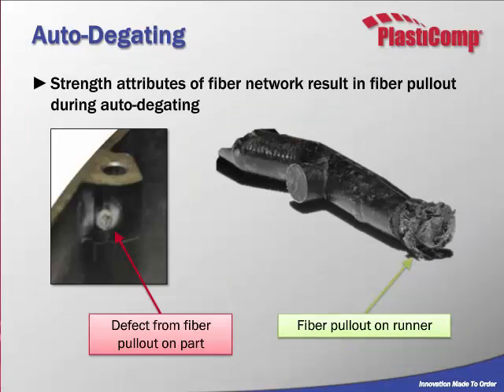Okay, another point along those lines is that auto degating gets a little bit trickier when you have these wider gates. These long fibers are quite strong, which in this situation makes things a little bit tricky. If you auto degate, you could get fiber rip out from your part. As long as it's not in a cosmetic area, that's not really a concern, but if it is in a cosmetic area, you have to think about that.